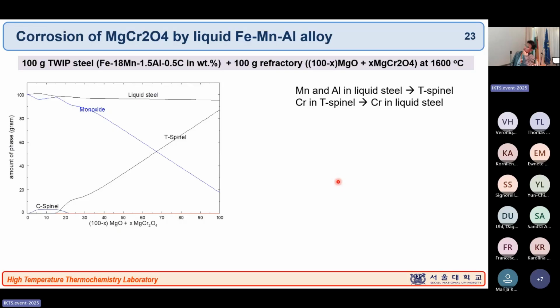For example, this is TWIP steel production: 18% of manganese and 1.5% of aluminum with 0.5% of carbon. That's a typical TWIP steel composition. And then they want to use the magnesium chromite refractory, MgCr2O4, typically known as a very stable refractory. But if you actually do this chemical reaction, is MgCr2O4 really stable under this condition or not?